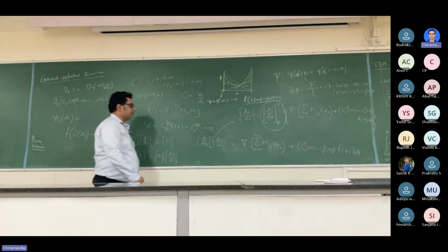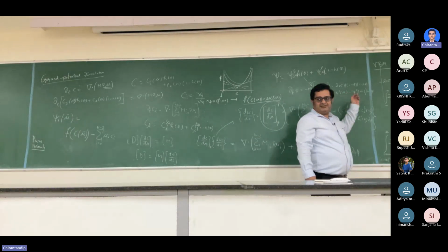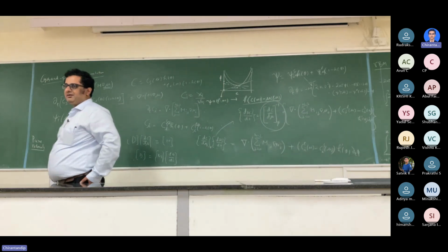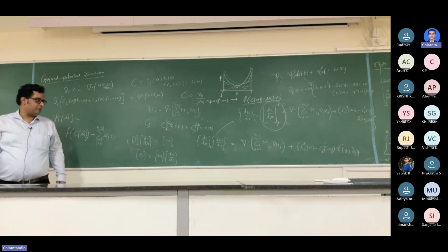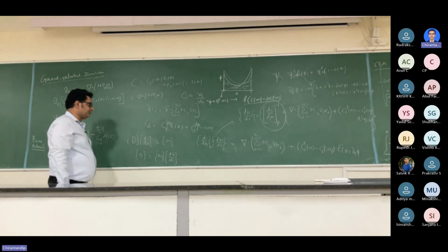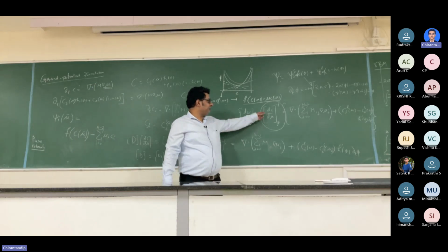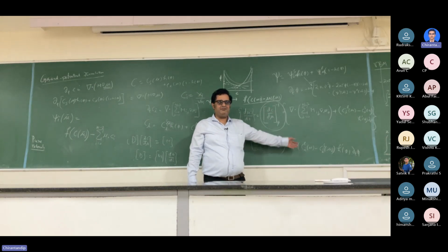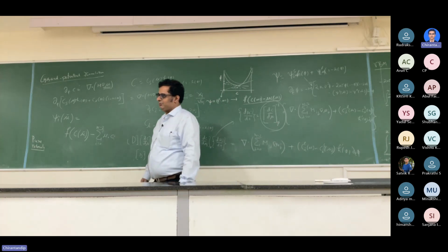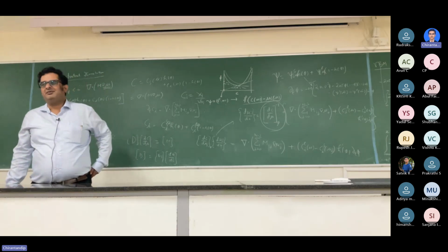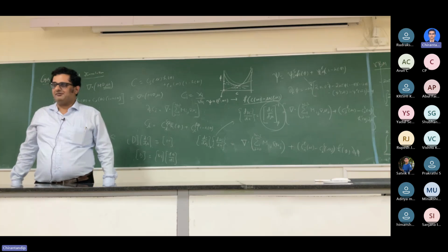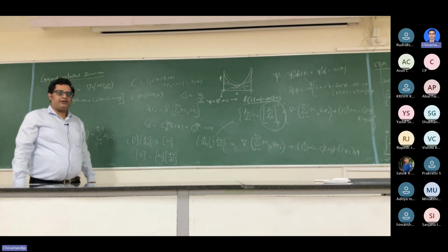And once you have transformed that, the remaining procedure is exactly the same as the binary. So the extension from the binary to multi-component was essentially quite trivial. The only thing is, in the pure binary case, this inverse would just mean 1 by dc by d mu. As soon as you have multiple components, it requires a matrix inverse. That's the not nice part, but something that you pay for having a nice elegant form. Good. Any questions?